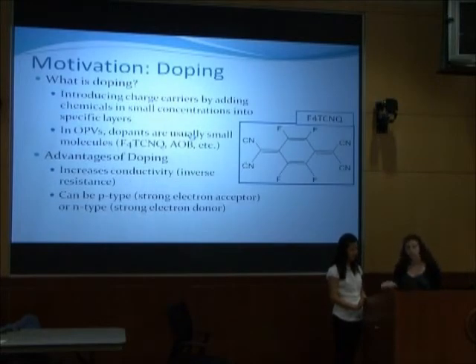Our objective is doping, but what is doping? Doping introduces charge carriers by adding a very small concentration of materials into specific layers of a device. Dopants are usually small molecules such as F4TCNQ, its chemical structure is pictured, and AOB. Doping is good because it increases conductivity in devices, and it can also be P-type, which removes electrons, creating a strong electron acceptor, or N-type, which adds electrons, creating a strong electron donor. Changing the number of electrons and the energy levels can actually change the placement of energy levels. And if these levels can move closer to the anode, you can facilitate a better ohmic contact.